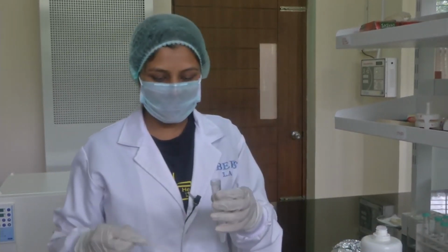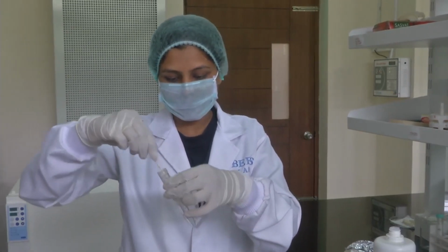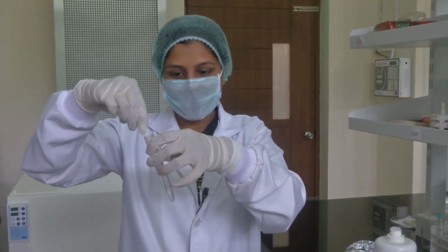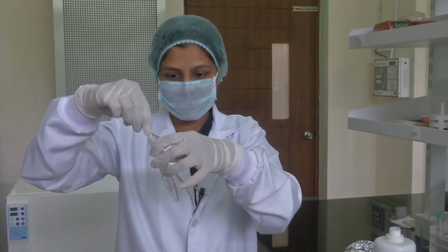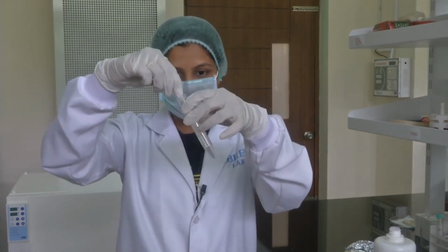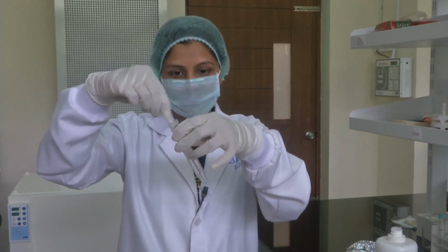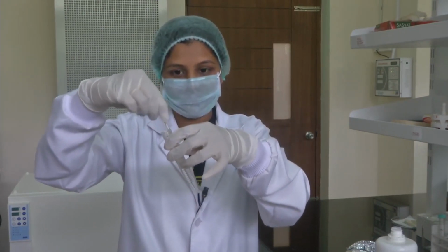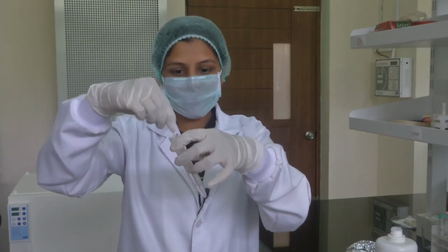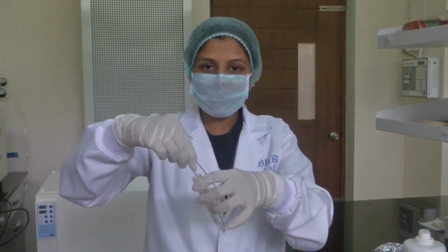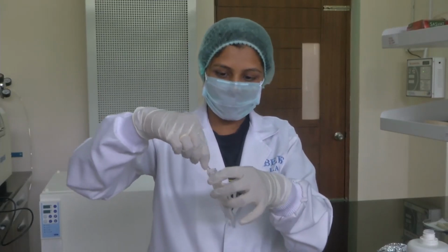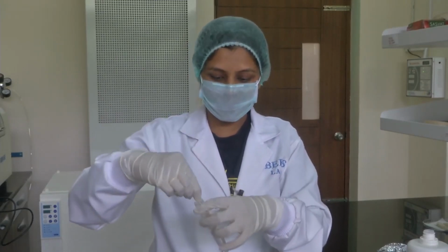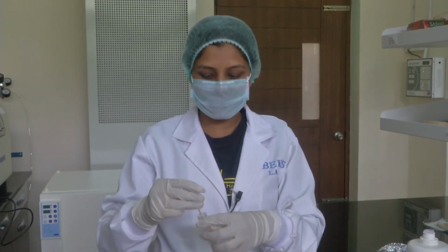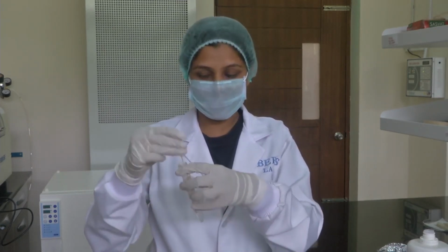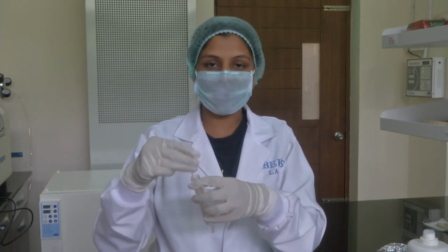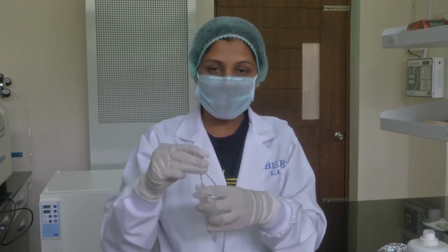So you could take a stirrer and then stir them thoroughly, and what happens while I do the stirring is, there are a lot of bubbles which get formed. So this process would go on. In order to combine the two immiscible polymers into a single liquid, you need to stir it for around 5 to 10 minutes thoroughly, so that the curing agent and the silicone elastomer are mixed.